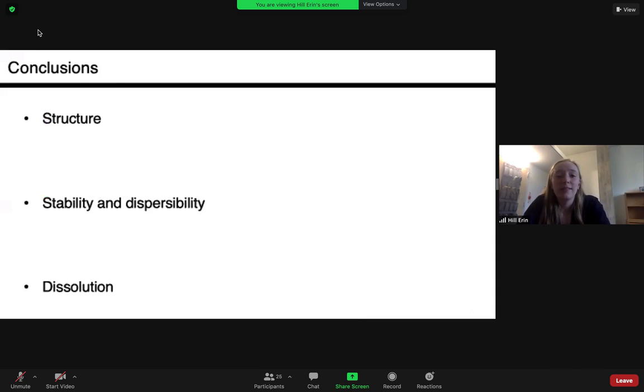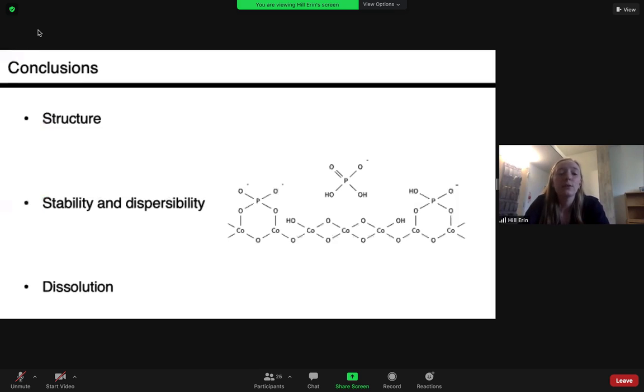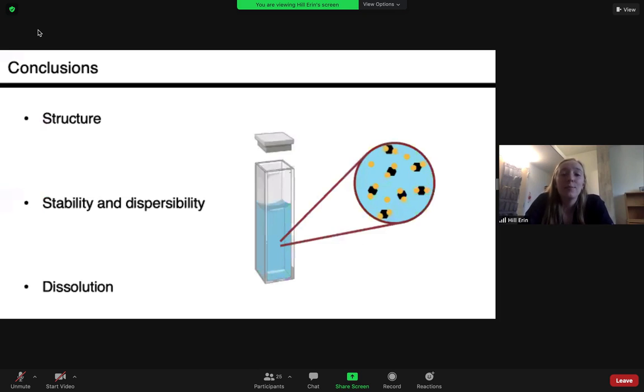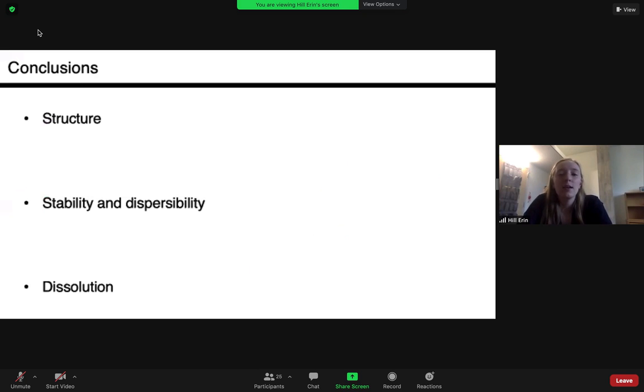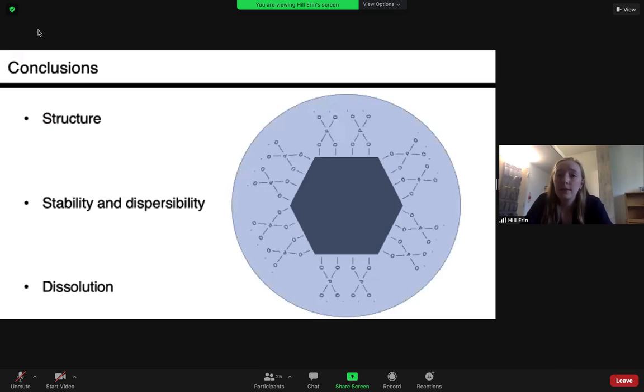So through this project, we learned that at environmentally relevant concentrations, phosphate bonds irreversibly to LCO, most commonly in that deprotonated bidentate coordination. This interaction changes the surface charge of LCO and stabilizes it in aqueous solution. It increases the dispersibility and reduces the sedimentation of the LCO nanoparticles. And finally, we saw that at low concentrations and fairly high concentrations for environmental standards, the dissolved lithium and cobalt did not see very different rates of dissolution in samples with phosphate and without.